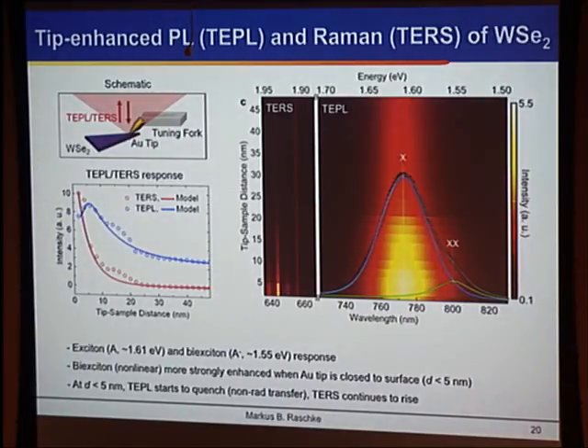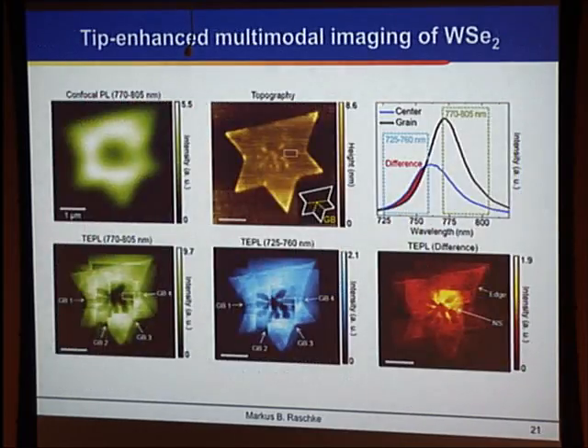And if you expand the lattice, then you shift the exciton frequency. With an expansion, the exciton frequency would decrease because you get a decreasing band gap, and vice versa, right? So we can do correlative imaging on these two parameters. And so we can get large field of view images in the near field. You see that increase in spatial resolution when we do the local probe with the tip. When we disengage the tip, you have conventional far-field limited spatial resolution.